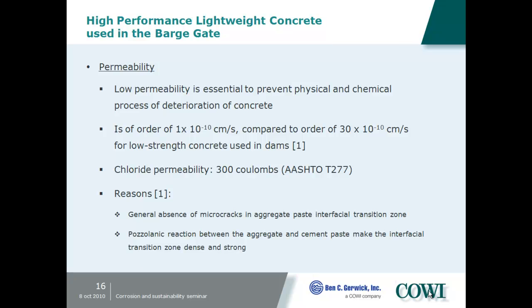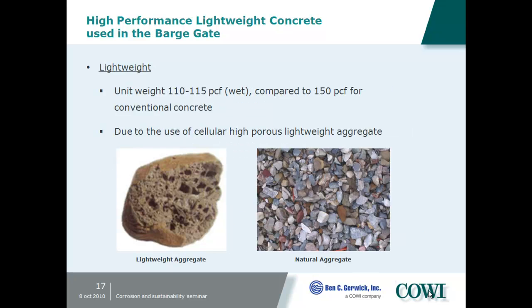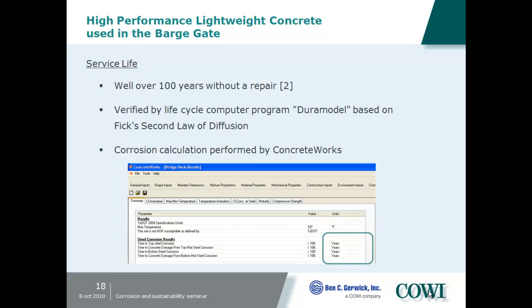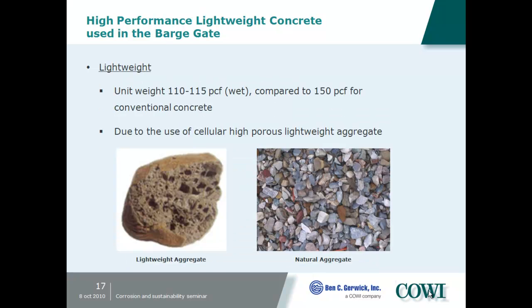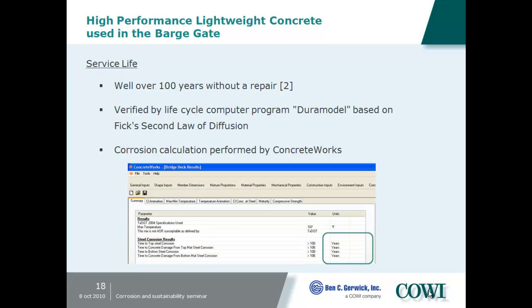It also has very low chloride permeability, so there's this Coulomb test monitoring the flow. So we did this on our mix design, and this is a relatively low Coulomb count, 300. And this we achieved, normally I think our average mix design here is about 112 pounds per cubic foot wet, and then if it hydrates, it could dry out with time. It should absorb less moisture because it has low permeability, so its density shouldn't be changing. You can see that, for those who don't know, this is made from shale. So you put it in a kiln and it puffs up like Cocoa Puffs. So it's almost like volcanic pumice in that regard. It's got a nice surface here to stop it from absorbing too much water.